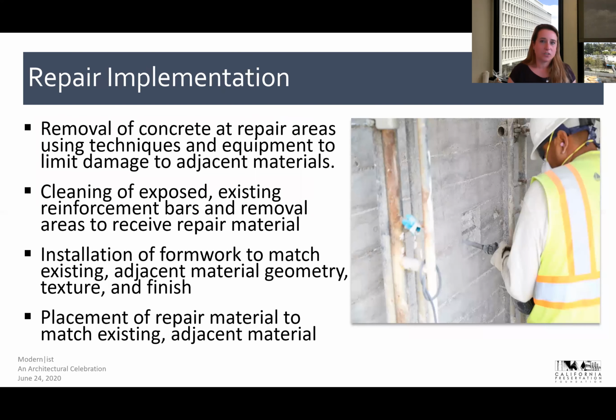So repair implementation, again, repairs for a sound and durable repair are going to be very similar to any concrete repair, whether it be a parking garage with little to no aesthetic implications or a warehouse. Ultimately, enough material has to be removed to remove any unsound material and address the deterioration mechanism, the distress mechanism. And again, if that's corrosion, you need to go behind the bar. So you may be taking out some sound concrete there to get behind the bar because you don't want to leave corroding bar in place or corrosion product in place.